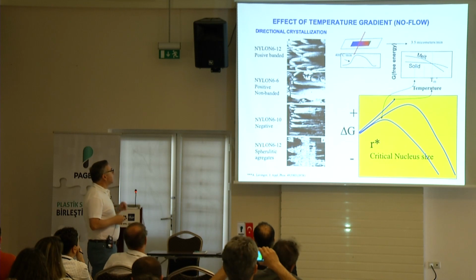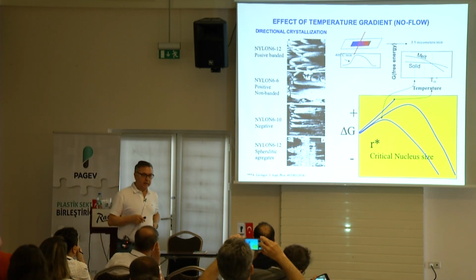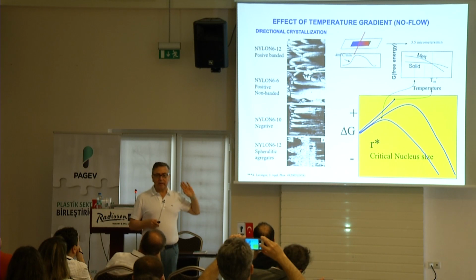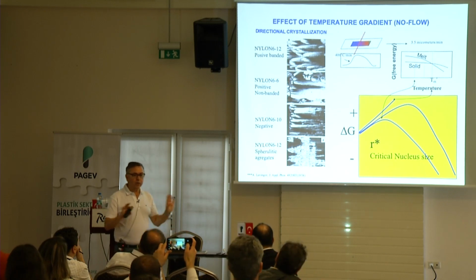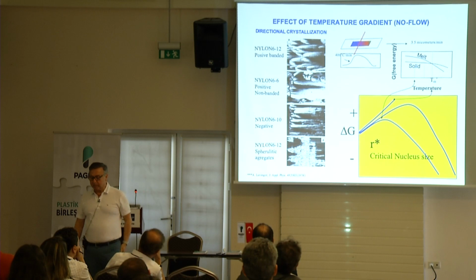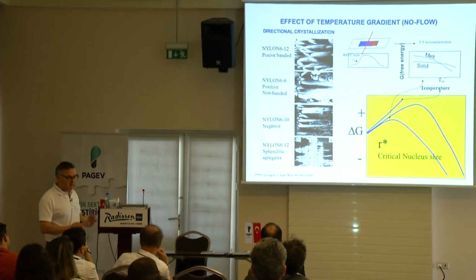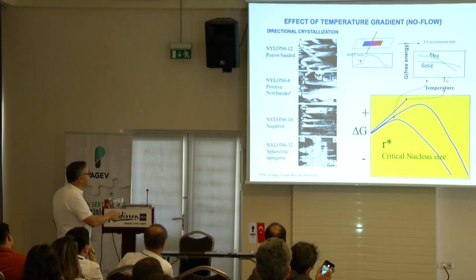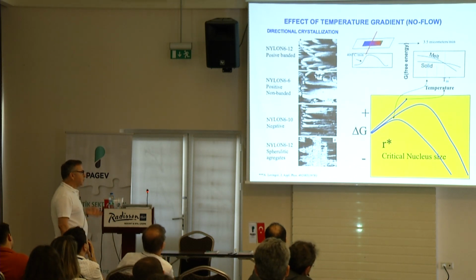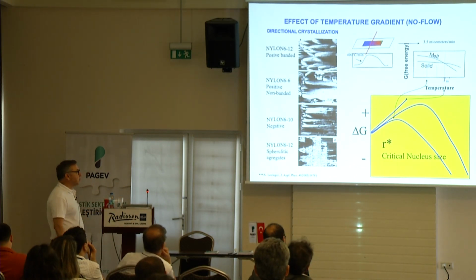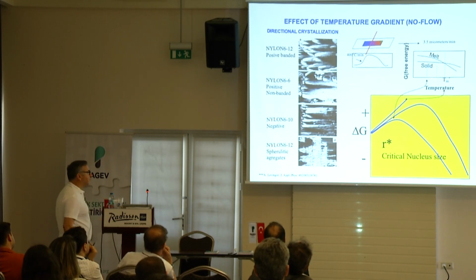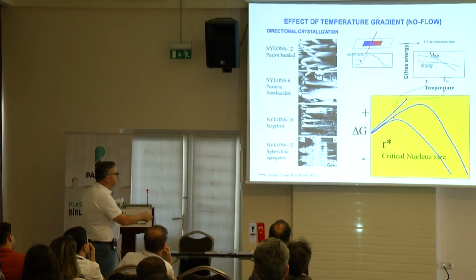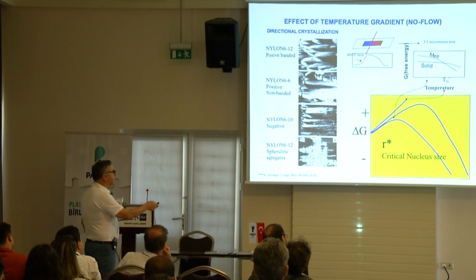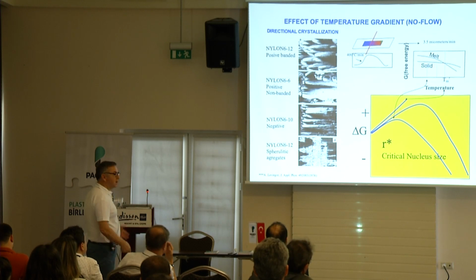All right, so what happens when you apply a temperature gradient? When you suddenly change the boundary and cool it down, but no flow. We're coming to injection molding. So this is the case where still there's no flow, and I change the wall temperature suddenly from melt to some low temperature. I just dropped it. So above the melt, this is the energy curve. It just keeps on going up. There's no way you're going to go back down because there's no critical nuclei size. You will never crystallize above the equilibrium melting temperature, period.